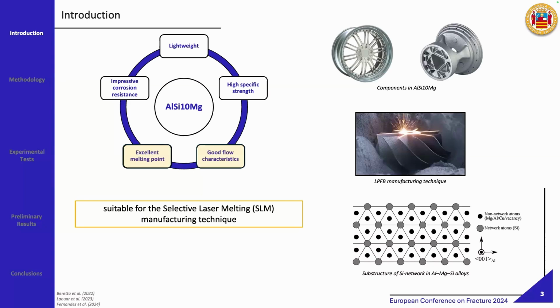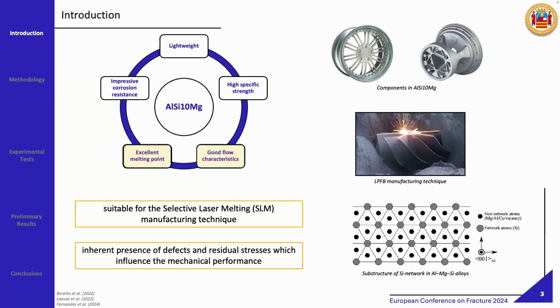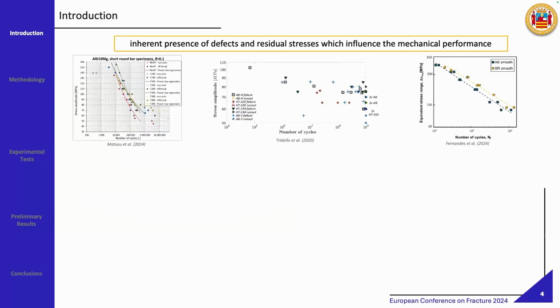In general, we know that specimens or components made with these innovative additive manufacturing techniques are intrinsically subjected to the arising of defects and residual stress fields, which inevitably jeopardize the mechanical performances. So in literature, there are many works which explore how to enhance and improve the mechanical performances, taking into account the presence of defects and residual stress fields, especially in presence of fatigue loadings. All these works, for example, take into account the use of heat treatments or stress relief approaches for enhancing the mechanical properties, but the greatest part of them is focused on constant amplitude fatigue loadings.